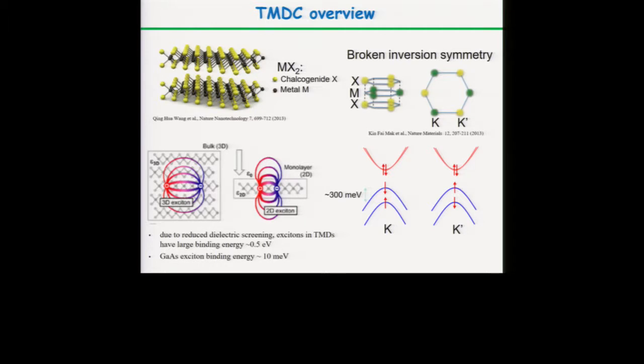They have a gap of around 2 electron volts, and also they have a spin splitting in the conduction band and valence band. The spin splitting in the valence band is around 300 millielectron volts, and the spin is different between each valley. So that's why they talk about valley and spin locking.